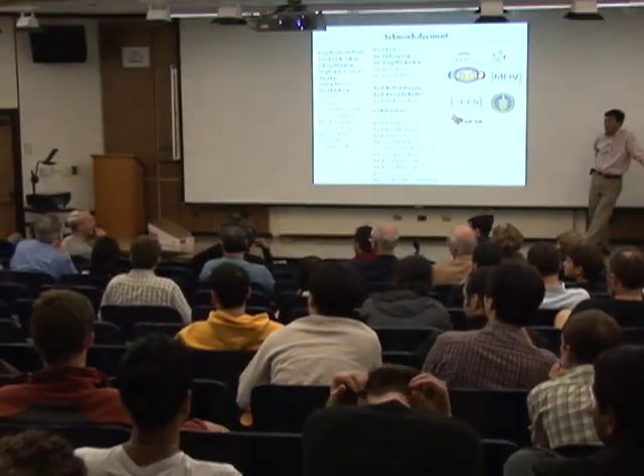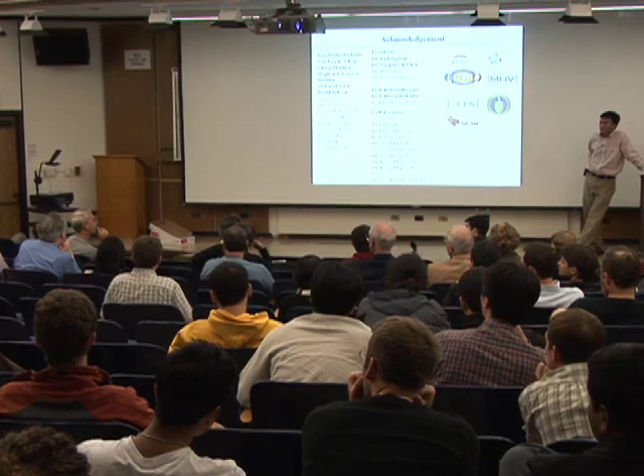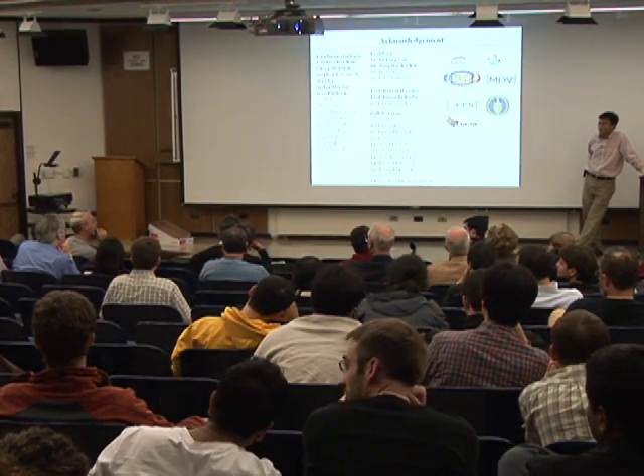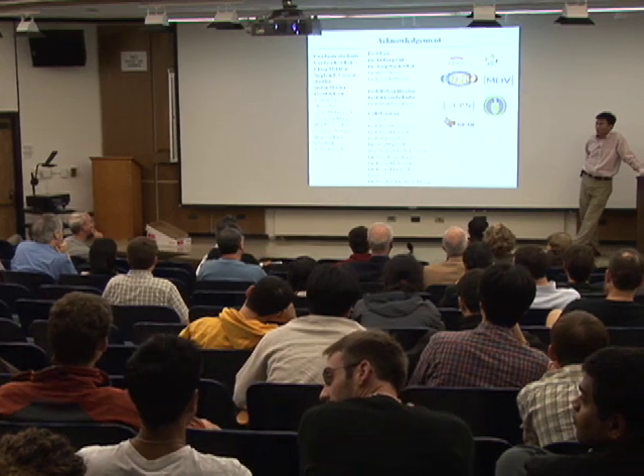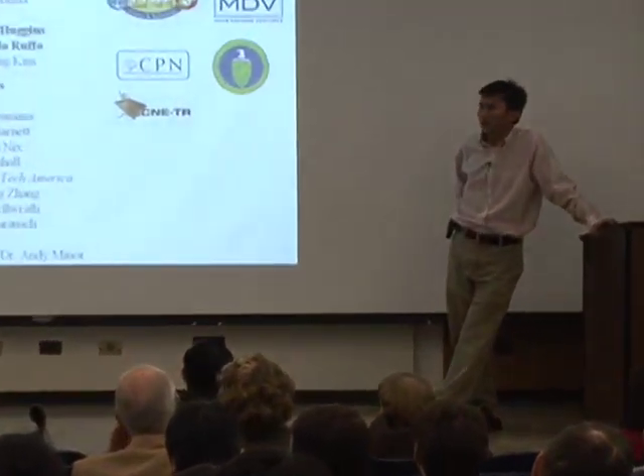You didn't talk about the cathode much, but if you nanostructure the cathode, are you concerned that the increased reactivity might increase the dendrite growth? Actually, no. As I said, silicon is actually better, for many reasons, at decreasing dendrite growth. Higher charge storage capacity doesn't mean the dendrite growth probability is increased. For the cathode side, we did have some study. Professor Kim is right here, and we have a nice collaboration on lithium manganese oxide. I didn't have time to talk about this, so we are working on that as well, how to improve the energy density, safety, cost, and everything about the cathode.